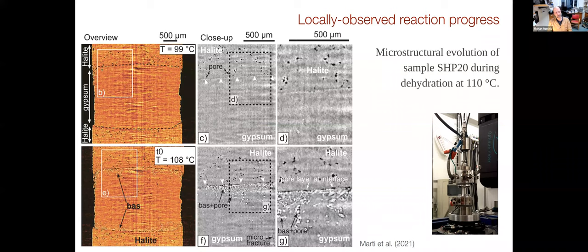and we look at our sample here. So the gypsum layer sits in the middle, that's unreacted at this point, and these slightly porous layers, which are non-permeable, but there's a little bit of residual porosity in there, which we couldn't get rid of, sit on either side, and they are sort of insulating or isolating the gypsum layer in the middle. Now, if we zoom in and we see this interface, and that will become important in a second, you can see there's not much going on.